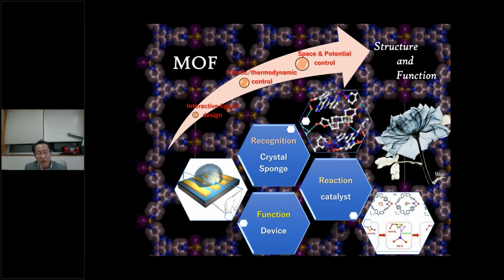Yeah, it's not easy. However, we succeeded in making a very interesting ligand. Then we combined kinetic and thermodynamic control. Then we created many kinds of MOFs until now. Also, we pay attention not only to space, but also to potential in the void. That means if you introduce redox activity in the ligand, you can create a redox active pore, a redox active void. Then you can create a very interesting porous material. So our research interest is exactly the correlation between structure and function.